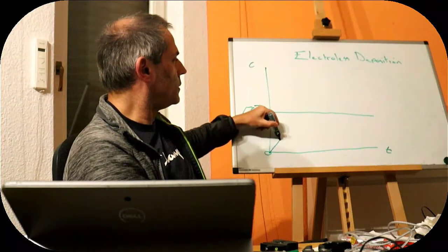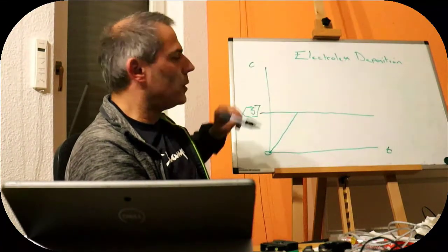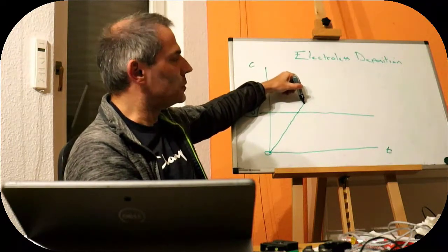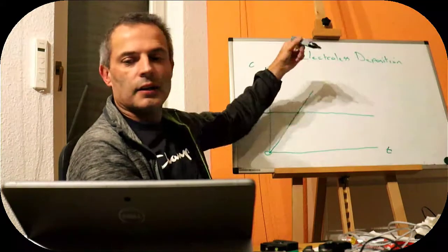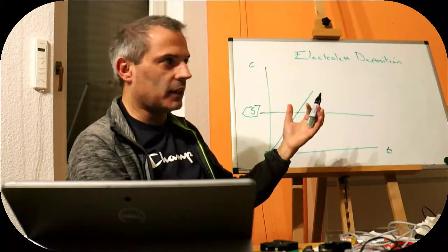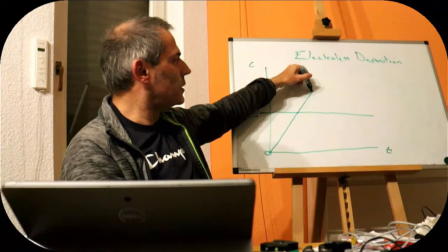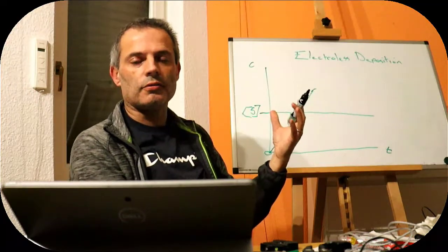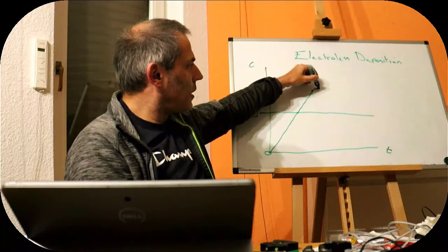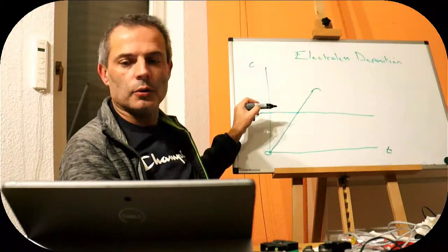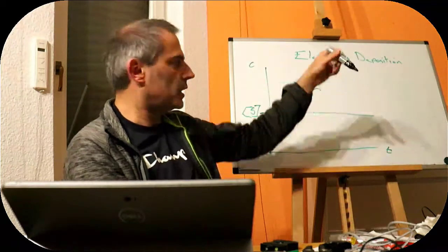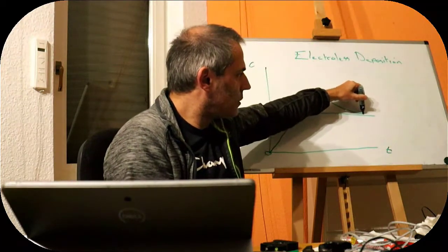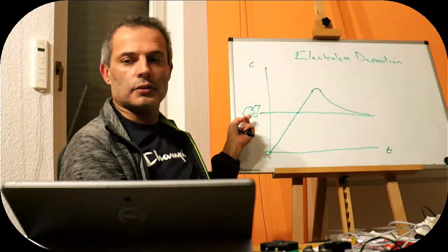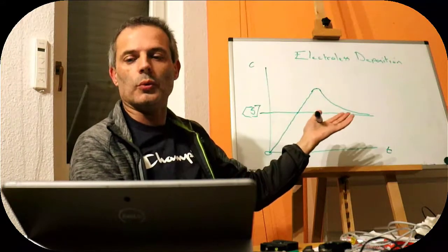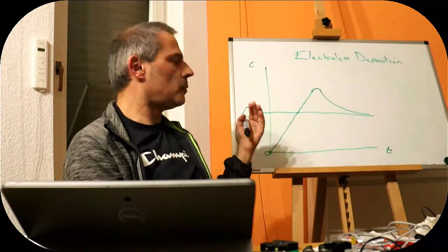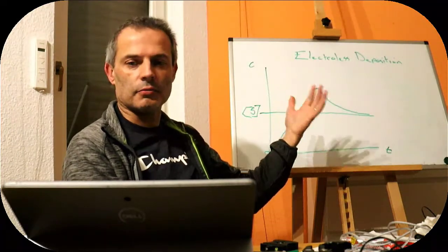So here we are, increasing our concentration. When we pass the solubility limit, nothing happens, and we make it supersaturated, and we can keep going, and then at some point we make it unstable enough that it starts to form particles. So we get a burst of nuclei formation, and then the concentration of our solution will come down, but it won't go past the solubility limit, because then it would obviously dissolve again. So then we will have some kind of approach to the solubility product where we would be at a stable situation thermodynamically. But we don't need to be at a stable situation thermodynamically any of the rest of the time.